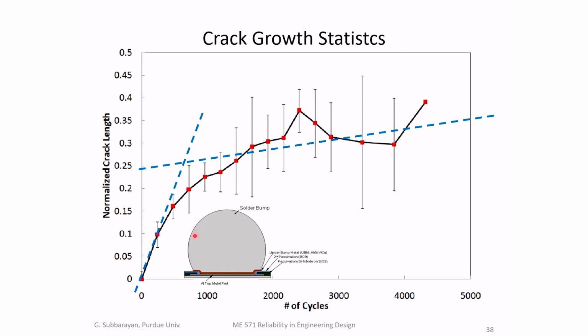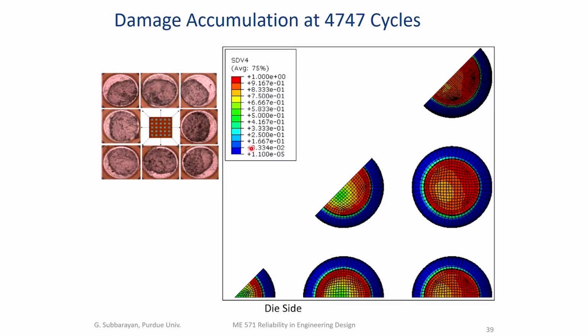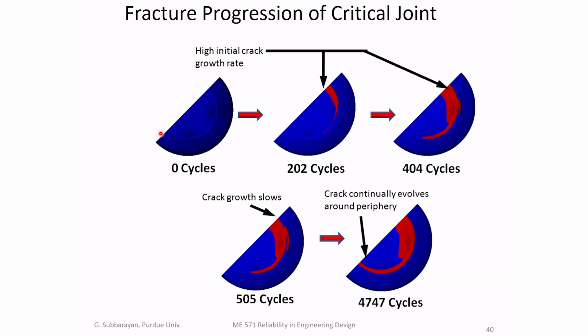So now we applied our max entropy fracture model to predict the crack. In the max entropy fracture model, the failure description was developed using isothermal tests. So the model does not have any data derived from the thermal cycling experiments. And here's the damage accumulated at a certain number of cycles. You can see that different joints on the package accumulate cracks at different rates, as you would expect, because they're all stressed differently. And on the critical joint, the corner joint, you can see the crack growth as predicted by the model. And of course, the model is independent of the thermal cycling experiments on the real product.